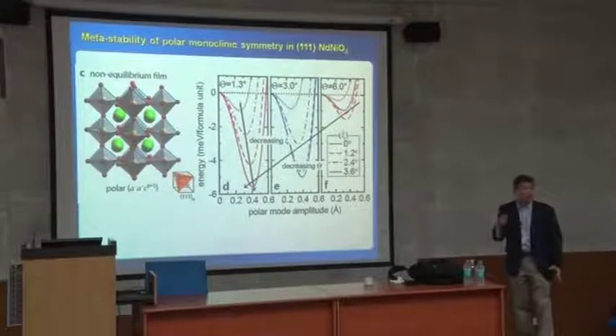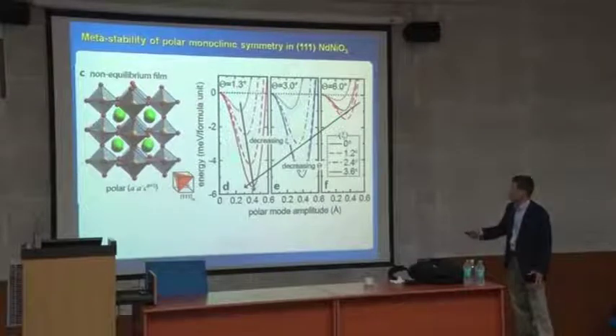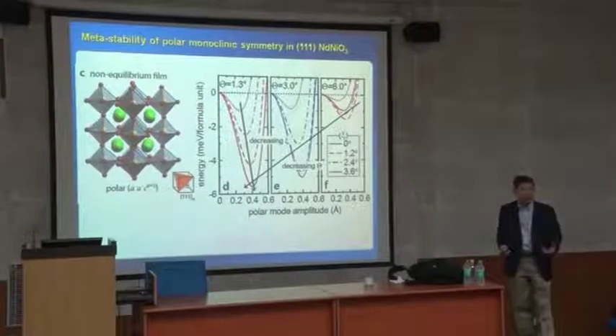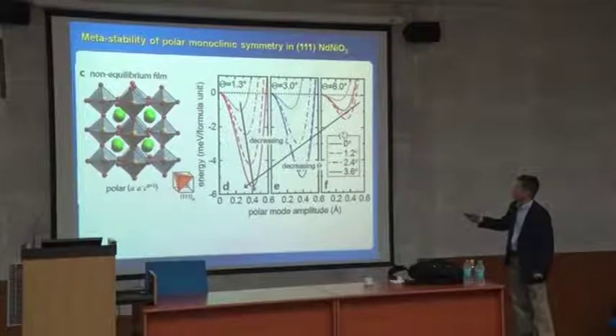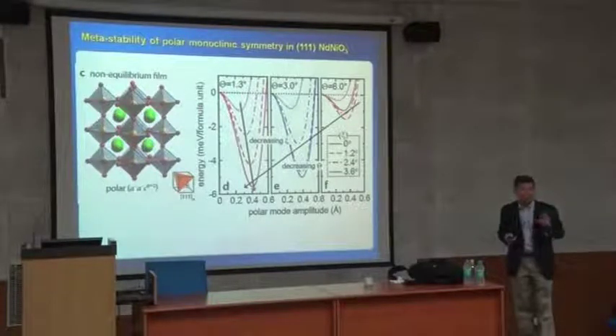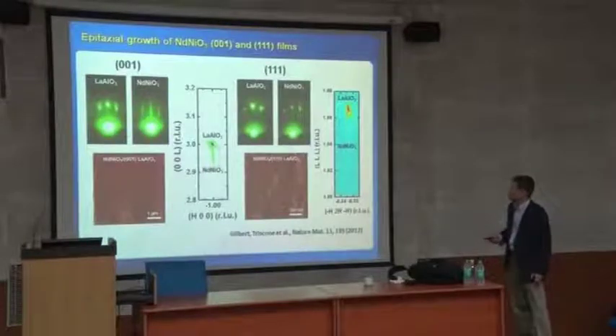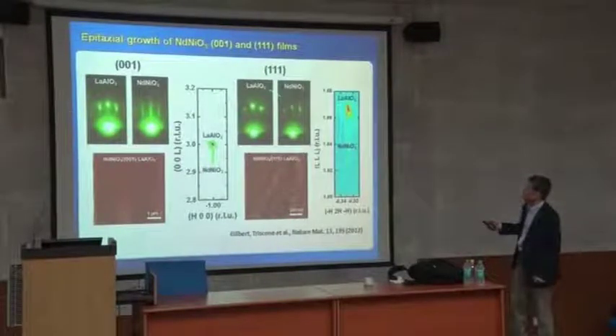So this is something the theory calculation shows: energetically more negative energy, which is more stable, and decreasing this tilting angle using this polar rotation, this actual rotation. So we do growth on this one, okay, 0-0-1 and 1-1-1, and then there are two types of different growth.